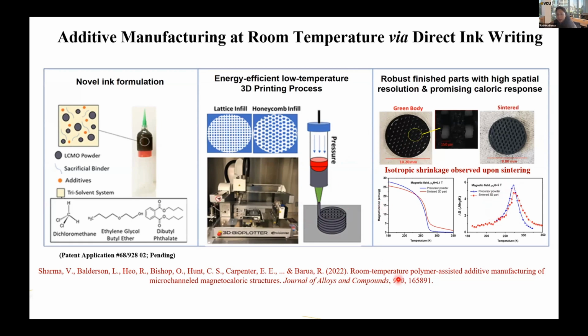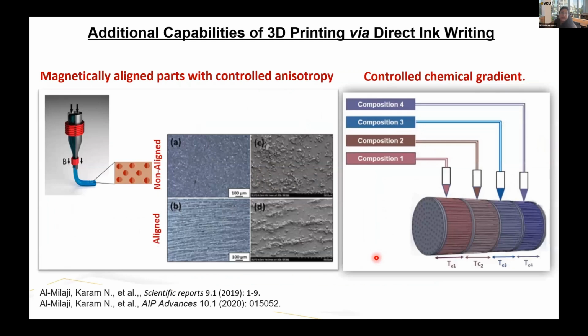So that's what most of Vaibhav's dissertation is actually focused on. He's been developing this direct ink writing work. The advantage is you can get anisotropic structures with direct ink writing. We've shown that you can put a magnetic field around the nozzle to get anisotropic microstructures, which would be great within a device. And if you use different nozzles, you can also get a controlled chemical gradient.